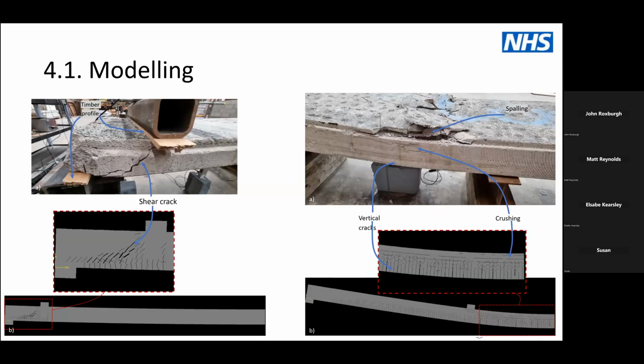So you'll see there what I mean by the shear crack at the support, that top left. So we tested some in the lab and they failed like this at times. But again, at a fairly decent load. If the steel's in the right place, they can take some shear load and it's okay. But if that steel is missing, then we have a problem.